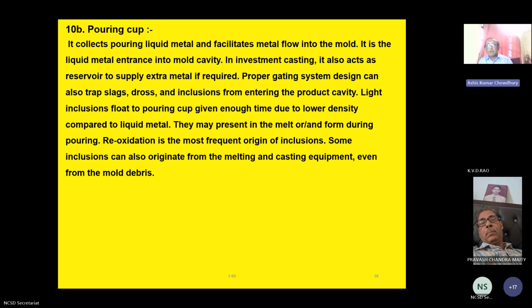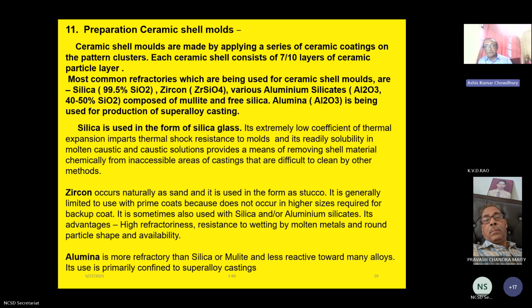Ceramic shell molds are made by applying a series of ceramic coatings on the pattern cluster. Each ceramic shell consists of 7 to 10 layers of ceramic particle layers. Most common refractory materials used for ceramic shell molds are silica, zircon, and various aluminum silicates composed of mullite and free silica. Alumina is used for production of superalloy castings. Silica is used in the form of silica glass.